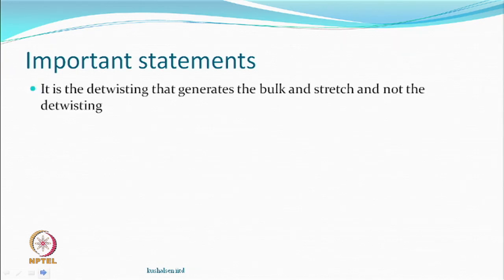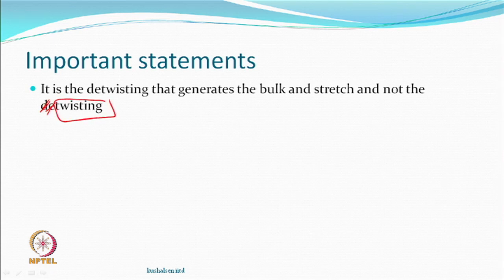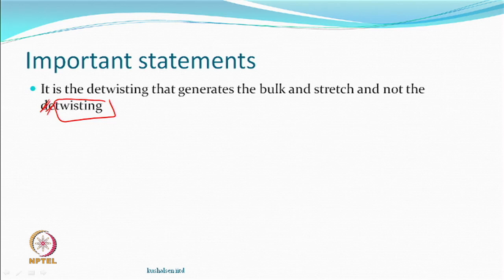Something to generally remember — I call these statements. It is the de-twisting that generates the bulk and stretch, and not twisting. Twisting is important, but by twisting you are not getting bulk and stretch. You cannot say that you will not twist and still get the same thing. But finally, it is the de-twisting which is responsible for generating the bulk and stretch.